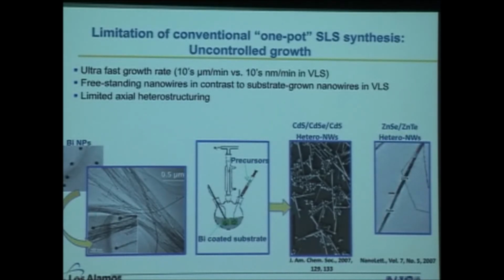And this is at Bill's lab, where they demonstrated zinc selenide, zinc telluride, axially heterostructured nanowires. These were grown in a flask, and he did it a couple different ways. One, he just added the different precursors sequentially, and they tended to get a nice kind of alloyed interface. If he took the first segment out of the solution, washed it, put it back into another growth solution, and added the next precursor, he could get a fairly clean interface. But again, it's a tedious process of washing, putting it back in a new flask, and so on. So clearly we didn't think that was too ideal.